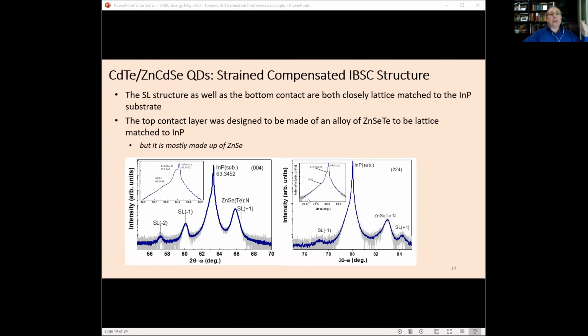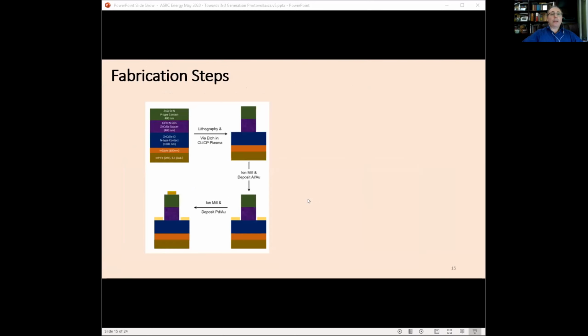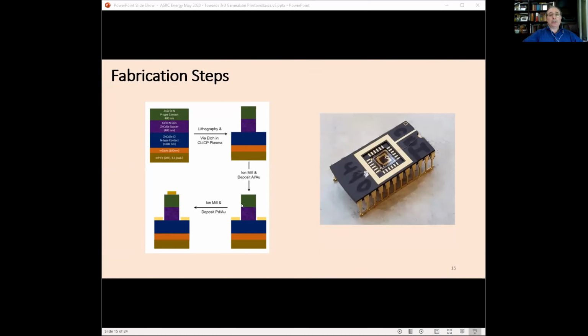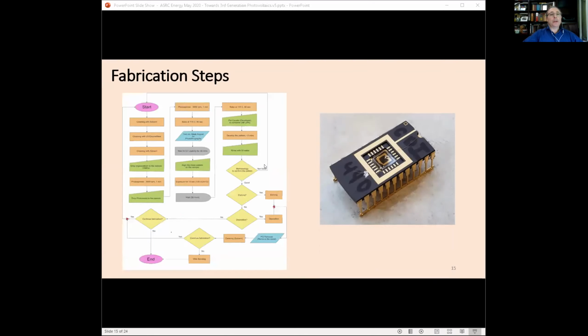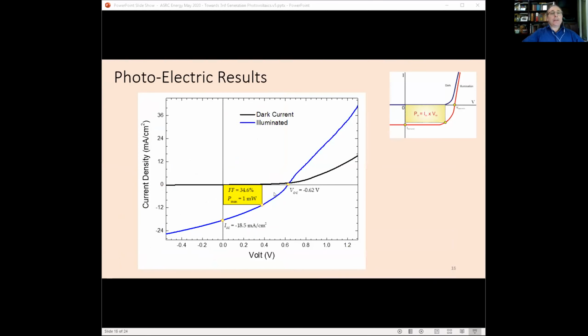Now, we actually managed to grow a strain compensation structure, which also reduces device defects and improves the quality of the device. So how can we do that? Those are the fabrication steps. They were done at ASRC. Without ASRC, we tried before, we couldn't do that. So that's the image of the final device. And if you think that's a very simple four step process, I just show quickly the flow diagram of what's actually involved. It's really complicated.